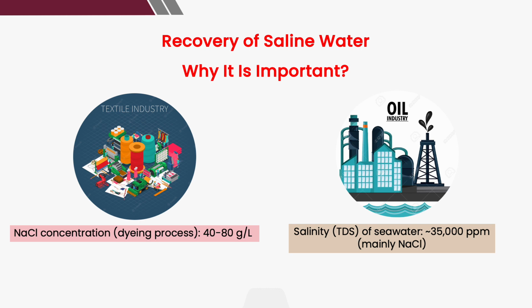So why do we have to recover the saline water from the wastewater? Why is it so important? And here I give you two examples. The first is the textile industry. The industry use a lot of NaCl, which is between 40 to 80 grams per liter during dyeing process. So NaCl in this case is compulsory during dyeing process to fix the dye onto a fabric.